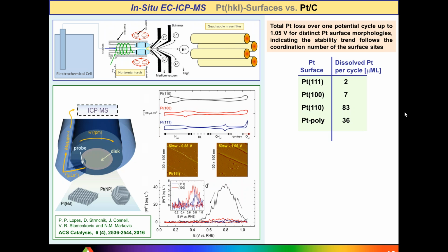So here is actually quantified result from single crystals, and you can see that the least amount of dissolved platinum is coming from platinum 111, which is in some way not surprising because this is a very close, densely packed surface. So in other words, those surface atoms have the highest coordination number among them, as opposed to platinum 110, which is the least stable, and for that reason that surface has the highest amount of dissolved platinum. So, and if we express that in factor, this is a substantial difference between those two. So why is all of that important?